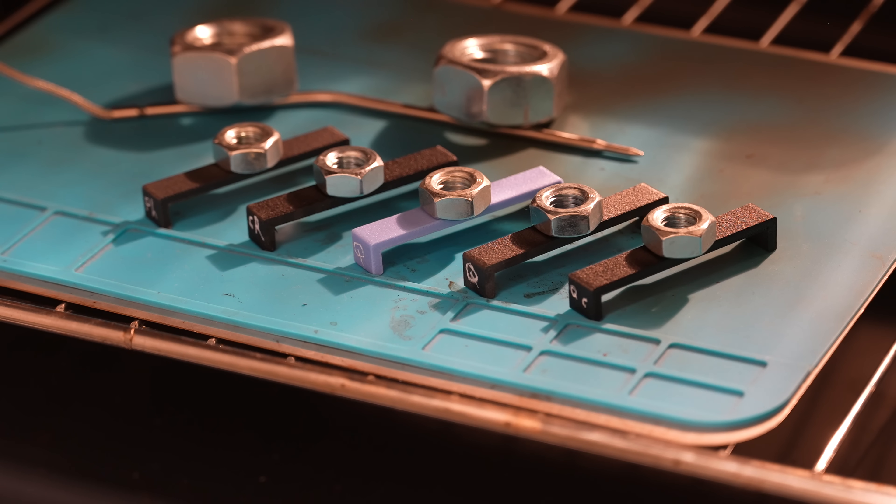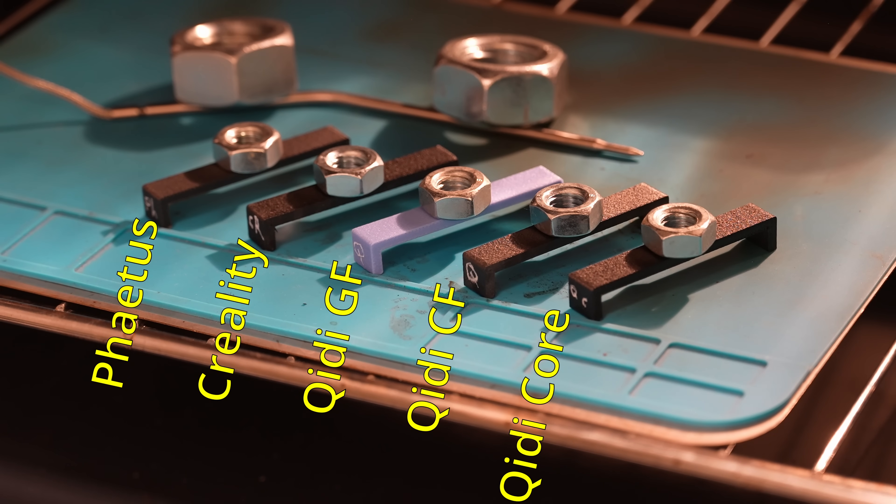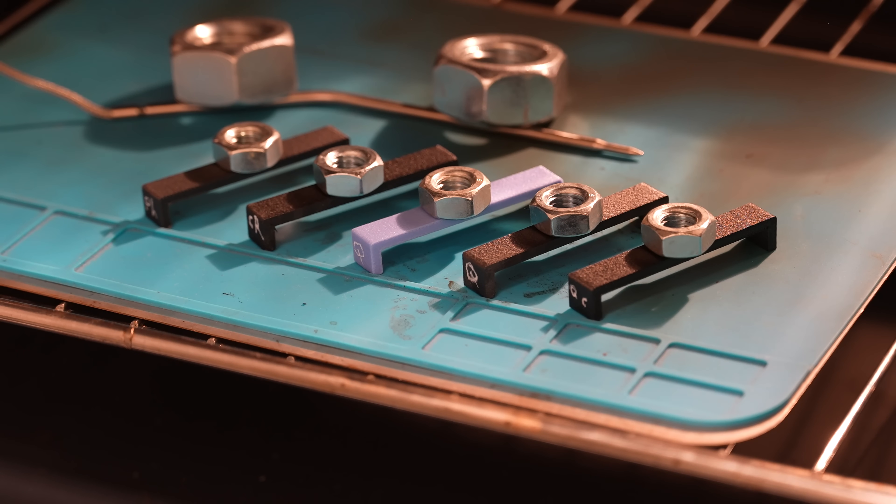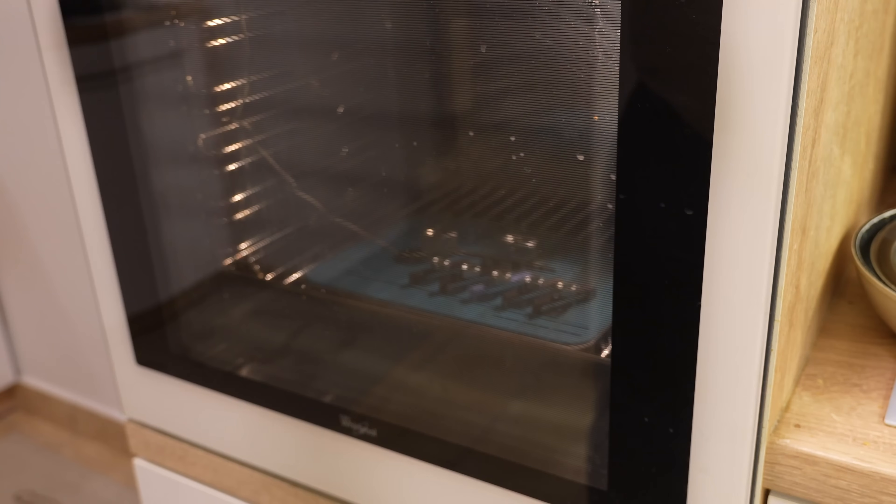Temperature test in the oven. I have several experiments in progress - these are all PPA-based materials. I believe this will be the most useless temperature test I ever did because I think I'll reach the maximum temperature of this equipment and there will be no deformation. This is end of the timelapse video. It was extremely hard to notice any start of deformation, but analyzing the footage it was approximately at 220 degrees Celsius.